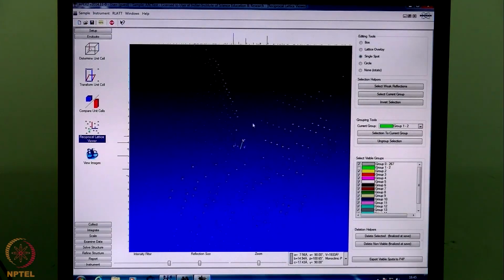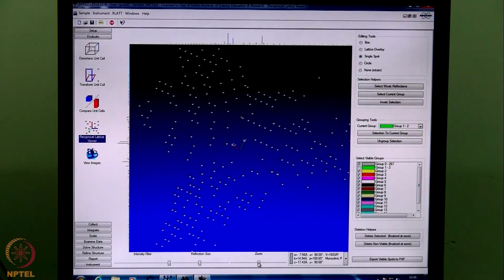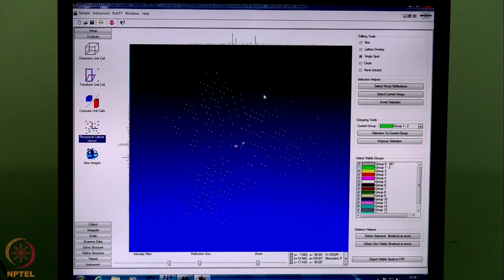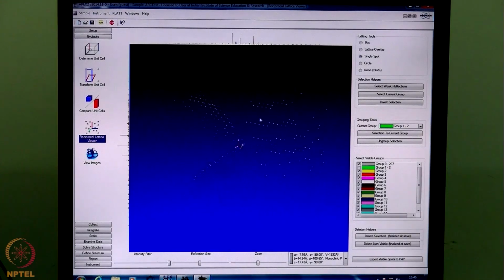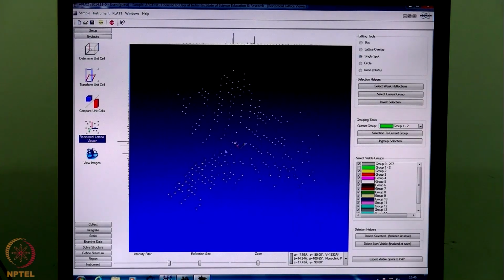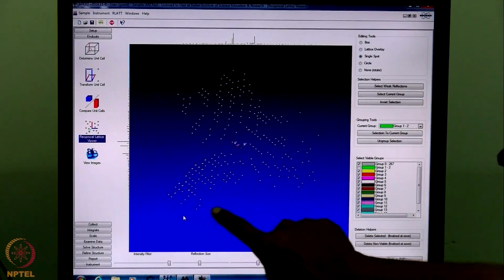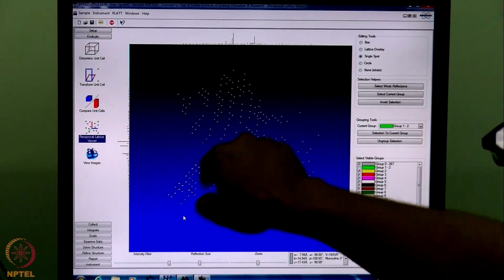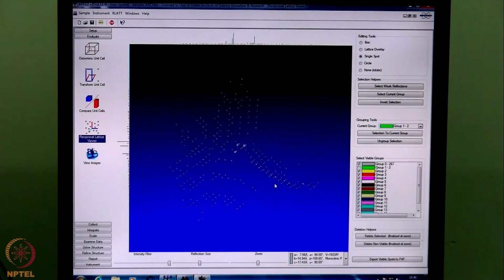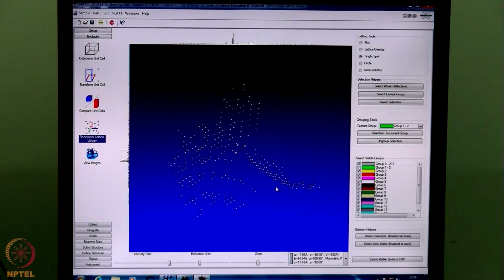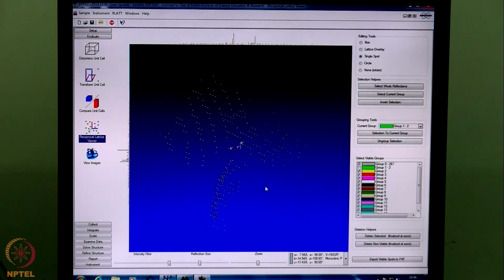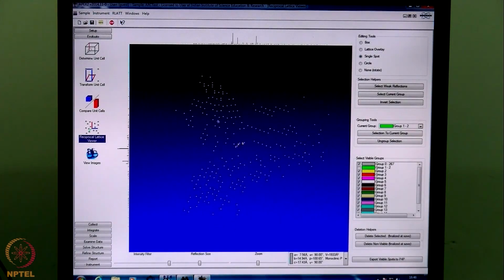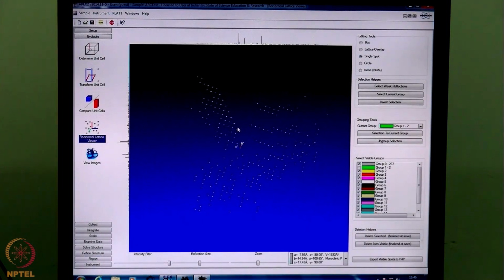See, what has happened is that this data was collected using 3 different orientations of the crystal, so it has scanned 3 different regions of the reciprocal sphere. These spots here represent one part of the reciprocal sphere, the spots here represent a second part, and the spots here represent a third part. This is how the diffractometer geometry is pre-aligned and pre-adjusted, so that the data collection strategy for unit cell determination scans at least 3 different regions of the reciprocal lattice and gives us very accurate unit cell dimension information.